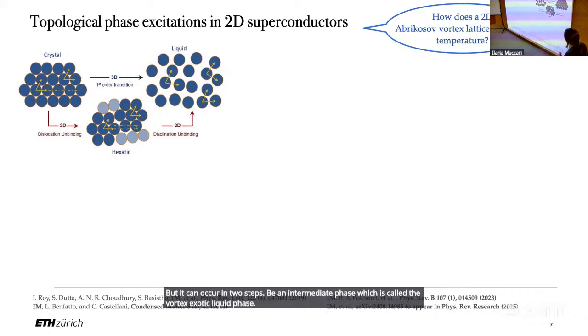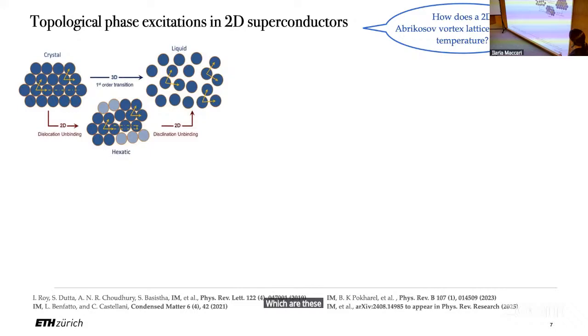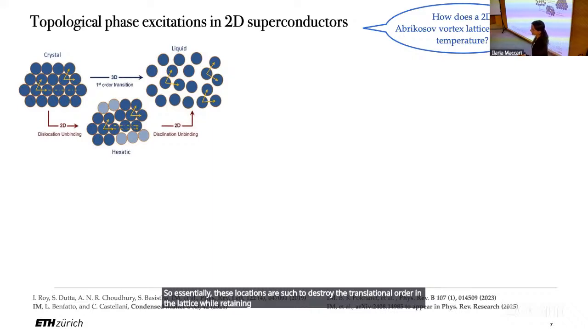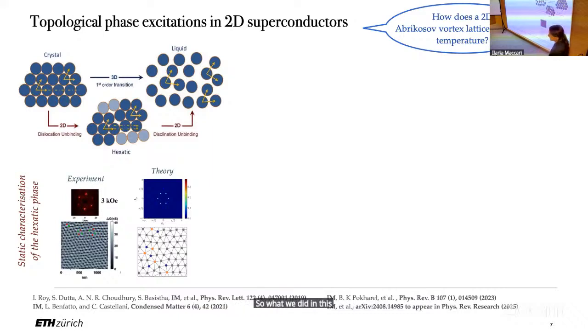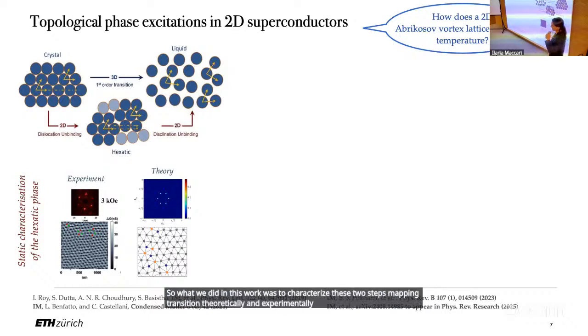This phase is reached via 2 continuous phase transitions driven by topological defects, which are dislocations in this case, and disclinations in this other case. So essentially, these dislocations are such as to destroy the translational order in the lattice while retaining an orientational order. So this hexatic vortex liquid is a sort of liquid crystal. There is still order with respect to the orientation of the vortices. So what we did in this work was to characterize these 2 steps melting transition theoretically and experimentally via 2 methods. So looking both at the static properties, meaning essentially how the vortex lattice evolves in temperature, which tells us about the proliferation of the defects.